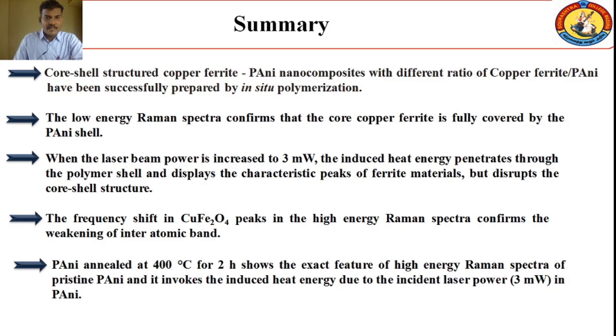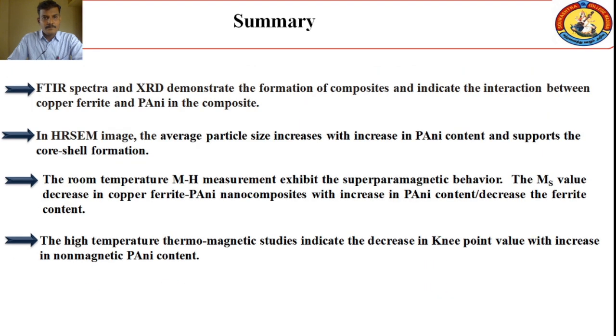In summary, we can conclude we have first synthesized copper ferrite polyaniline nanocomposites by using the in situ polymerization technique with different compositions, and the core-shell structure is confirmed by Raman spectrometer with different energies, and that is also confirmed by XRD, FTIR and HRSEM analysis, which also confirmed the synthesis of core-shell nanocomposites.